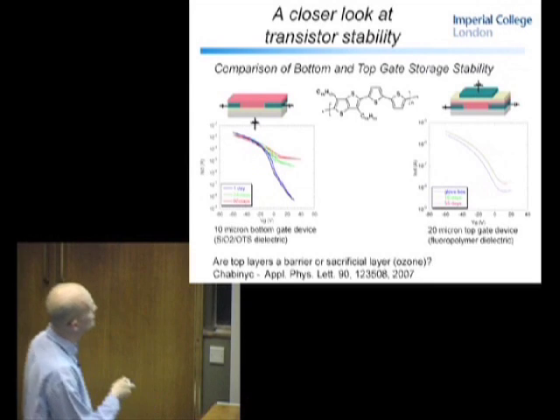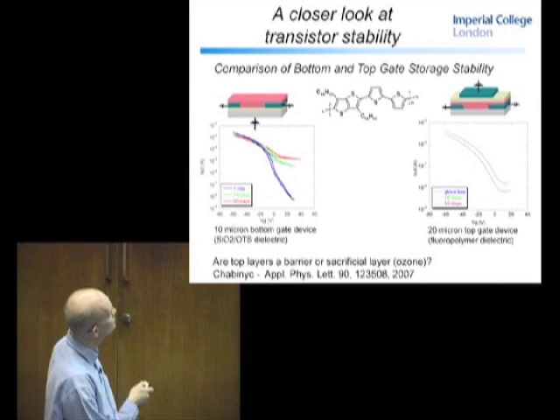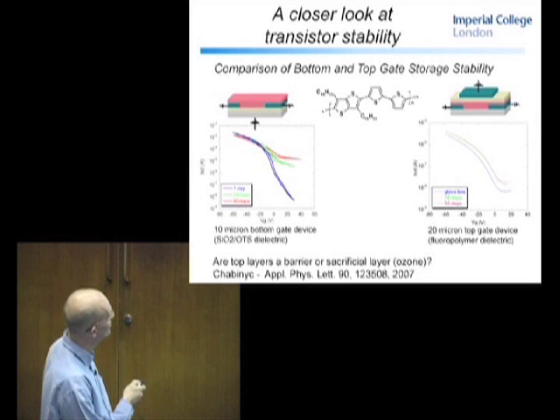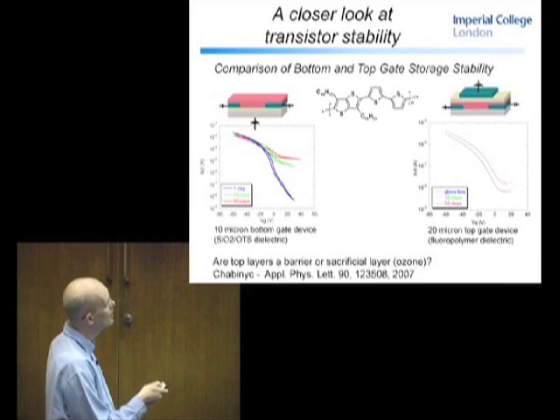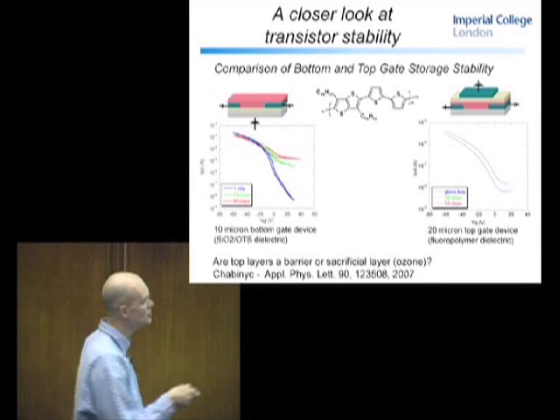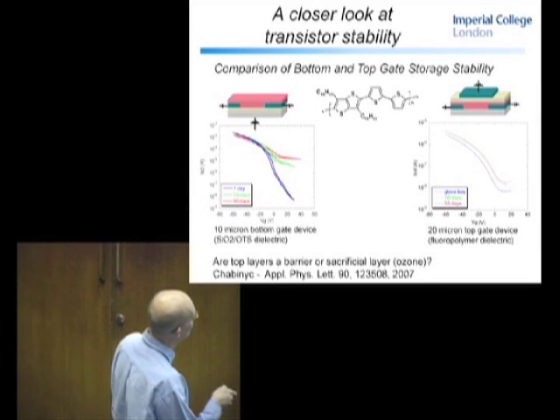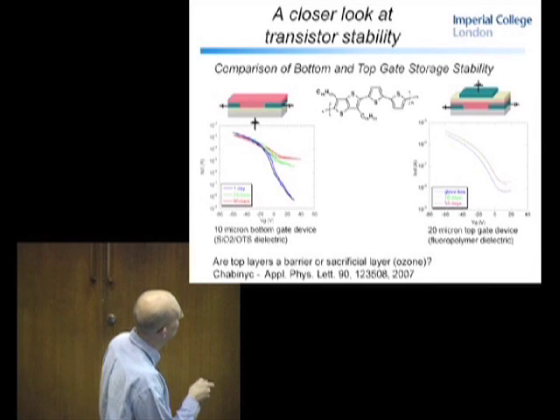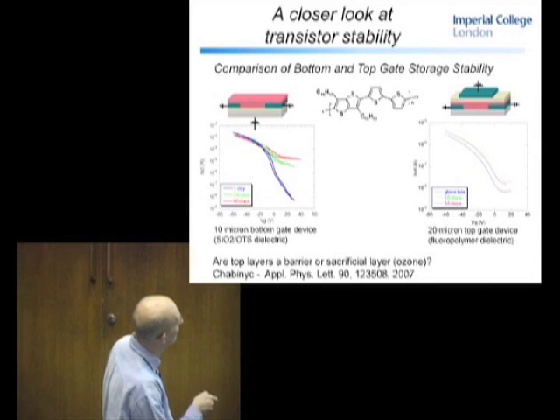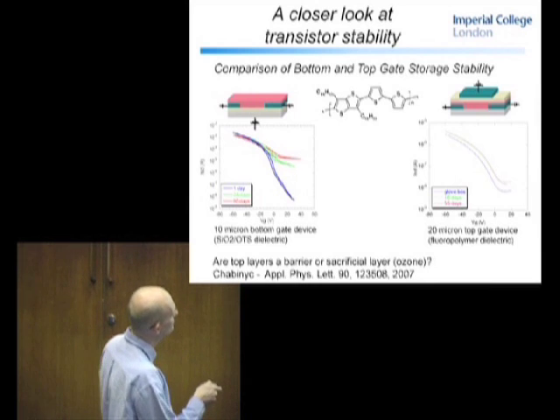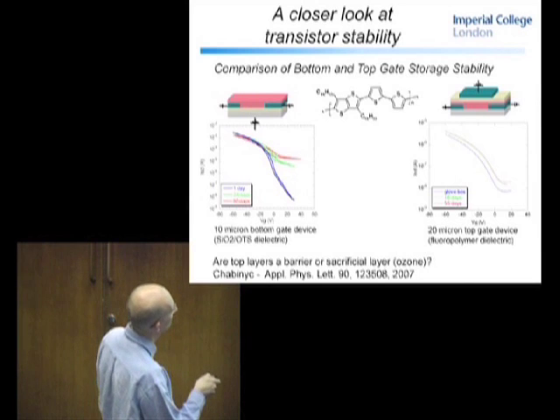So I did have another slide on this. If you compare top and bottom gate architectures, this is a bottom gate architecture. In this case, the semiconductor is completely exposed to ambient conditions. In this case, you've protected the semiconductor with the dielectric and the gate. And it's hard to exactly compare because you need different dielectrics in both cases. But in a bottom gate device, after 90 days or whatever, you see big differences in the off current. Orders of magnitude jump up. So it seems to have doped quite a lot. A little bit more hysteresis, not looking quite so good.